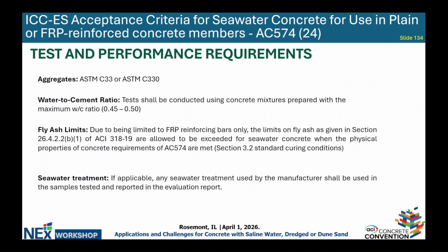Aggregates. At this time, for normal weight concrete, we're just requiring ASTM C33, and for lightweight concrete, ASTM C330. The water to cement ratio has to be at the maximum water cement ratio between 0.45 and 0.5. And we actually allow the fly ash limits that are given in section 26.4.2.2B1 of ACI 318-19 to be exceeded when the physical properties of concrete requirements of AC574 are met.